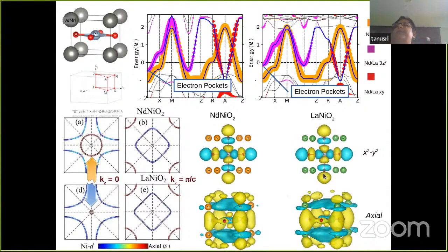And this is also evident if you look at the Wannier function that describes these two bands. They are quite similar for this orange colored band, which basically shows it is nickel x² minus y², that makes an antibond with the 4 neighboring oxygens, and pretty similar looking. But the other Wannier function, which we call an axial orbital, in the same spirit as that of the cuprate, the shape of this axial orbital is actually quite different between neodymium and lanthanum. Lanthanum being much more spherical, while it is much more cylindrical in case of the neodymium compound.